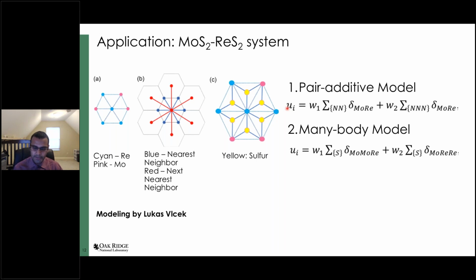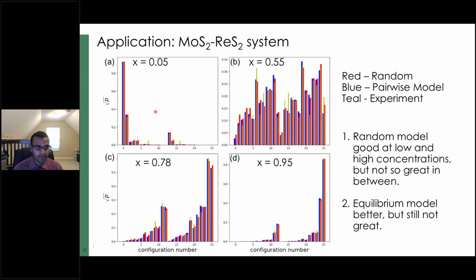And so again, just like the previous example, we will take our images and convert them to histograms of atomic configurations. Only now we have not 6 configurations, but plenty more. We have about 26 configurations that we actually see. And we can plot how they behave for the different compositions. So this is the 5% rhenium case, and this one is a 95% rhenium case. And we can see how a random model compares to the pairwise model, as well as the experiment. What you see here is that the random model implies that there are no interactions at all. Everything is just random.